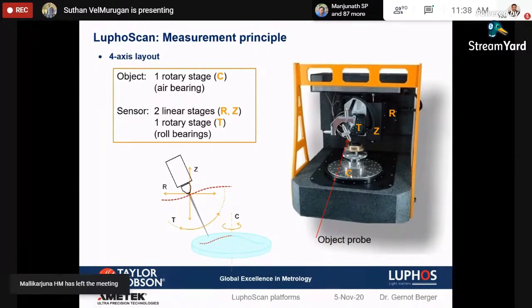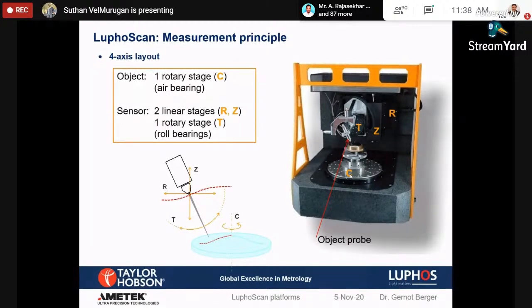For example, if we are going to cut some sample and we know this is a rough cut, not a finished sample, my error will be in the order of 200 to 300 nanometers. Probably we can rotate at a high speed up to 100 RPM or 90 RPM and measure it. And if you are looking for something like 25 to 30 nanometer form error, probably we need to reduce the speed to around 25 to 30 RPM. That can be defined, and that is the important part. We can define it before we start the measurement.